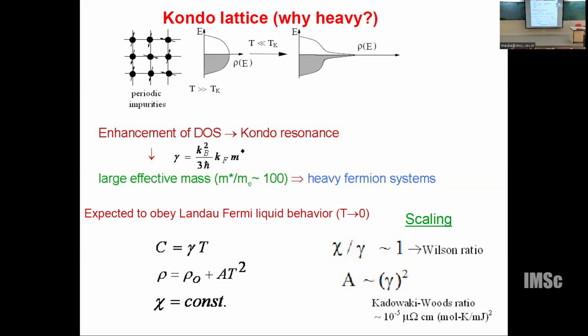This results in the renormalization of the bare density of states. Because of the mixing of the 4f electrons, they go out and come back, or hybridization or bonding, whatever terminology you use, you find a renormalized density of states at the Fermi level. These are questions which you ask. Therefore, this is also called the Abrikosov-Suhl resonance, in honor of the people who discussed it. There is a huge density of states, that is a narrow band, actually a very narrow band. It's called narrow band phenomena, with different terminologies. The narrow band is typically of the order of a few milli electron volts, or 10 or 20 of that order. It's not like several eV.